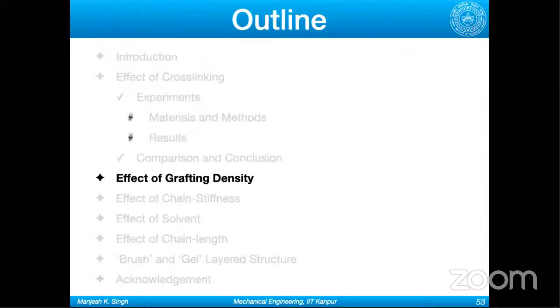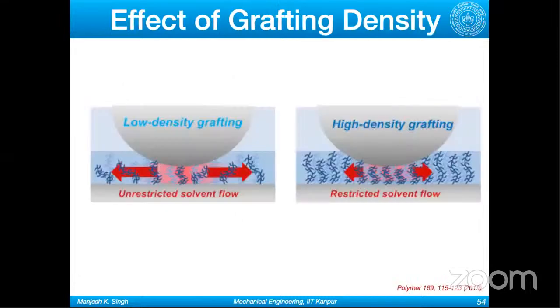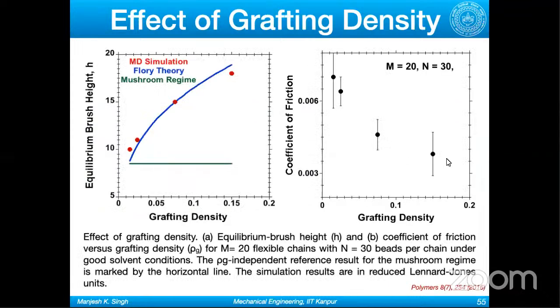I think my time is also closing. So, effect of grafting density. As I said, there are different parameters which will affect polymer-brush-based lubrication. If you have very low grafting density, there are fewer polymers to support the normal load, so the solvent will squeeze out. If you have high grafting density, they can support the normal load, and the solvent in between can help you reduce the friction. So as expected, if you increase the grafting density, the coefficient of friction will gradually go down.